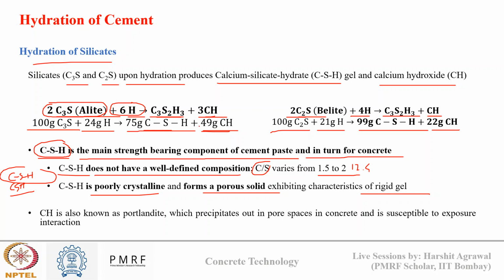While CH is also known as Portlandite. CH is nothing but Ca(OH)2. It is known as Portlandite, which is precipitated out in pores in concrete. When we talk about concrete, there are pores present in concrete. In these pores we'll find CH, which is leached out. This is an unwanted product in concrete. The product that we want for strength is CSH. CH is something which is unwanted.